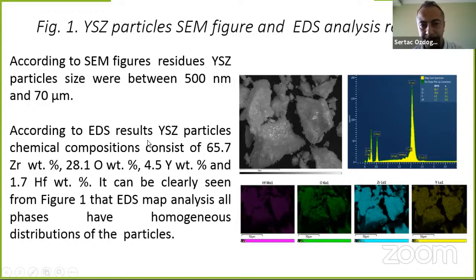According to the results, chemical compositions consist of 65.7 weight percent zirconium, 28.1 weight percent oxygen, 4.5 weight percent yttrium, and 1.7 weight percent hafnium. It can be clearly seen from figure 1 that in the EDS map analysis, all phases have homogeneous distributions of the particles.